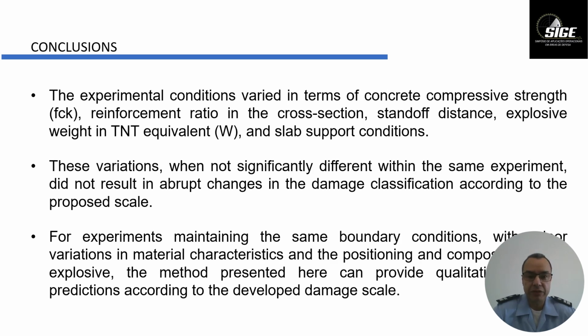So, the experimental conditions vary in terms of concrete compressive strength, reinforcement ratio, cross section, standoff distance, explosive weight, TNT equivalent, and slab support conditions. This variation, when not significantly different within the same experiment, did not result in abrupt changes in the damage classification according to the proposed scale. For experiments maintaining the same boundary conditions, with variation in material characteristics and explosive, the method presented here can provide qualitative predictions according to the damage scale.